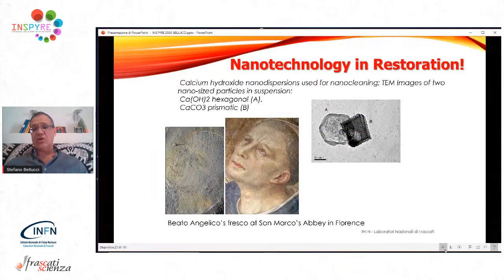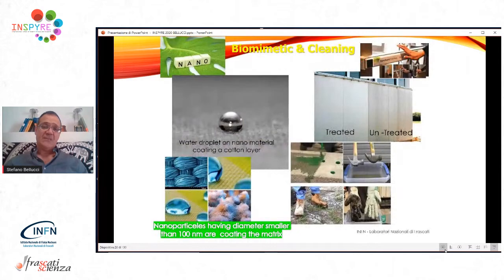Nanotechnology is also normally in use in cultural heritage. And here is an example of a fresco in Florence, where calcium hydroxide nanodispersions have been used for nano cleaning. So you see on the right-hand side the images at the transmission electron microscope of 2 nano-sized particles that are used in the dispersion or in the suspension. And they have different shapes, different structures. The A is a hexagonal calcium hydroxide. The other one is a carbonate, and it's prismatic.